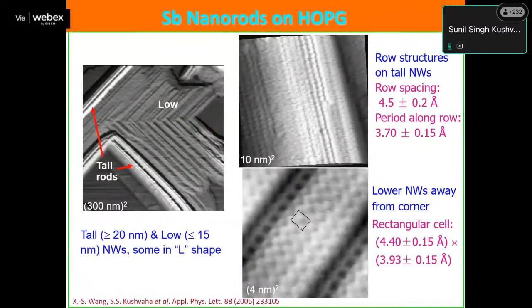The same thing we can do for the different structures, 3D, 2D, 1D. But once we go to the 1D nanorods, we see it is not the antimony 111 structure, but it is showing the antimony 110 structure. So even from the same material we have different structures, and different structures have different crystalline structure. That we can only do in situ, because we are not exposing the sample. We grow the film, and from the same chamber after growth we move to the STM stage without breaking the vacuum. The vacuum is always 10 to the minus 10 millibar. Then we are able to scan, and we can clearly see these kinds of crystalline structures.